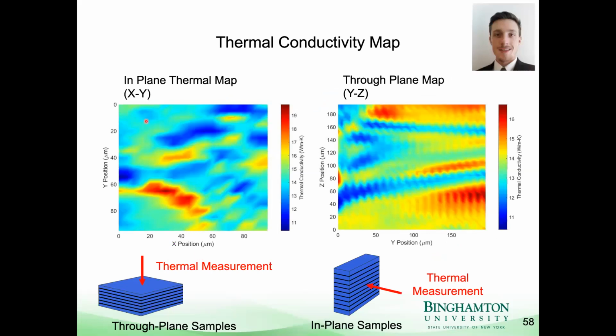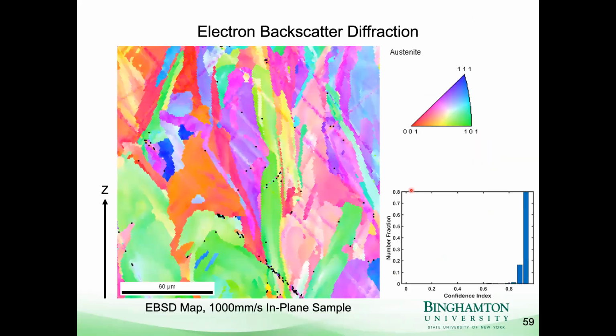So we next did thermal conductivity mapping. These are thermal conductivity maps that we made in the in-plane and through-plane directions. And just like we did with copper through tin, we tried to relate this to a microstructure. So we did electron backscatter diffraction to measure the orientation of different grains. And we thought maybe there'd be some relationship between the crystal orientation and the thermal conductivity map. But unfortunately, there was none. We also looked at elemental mapping, and we couldn't find a relationship between the thermal conductivity variation that we saw in the map and these microstructural properties.